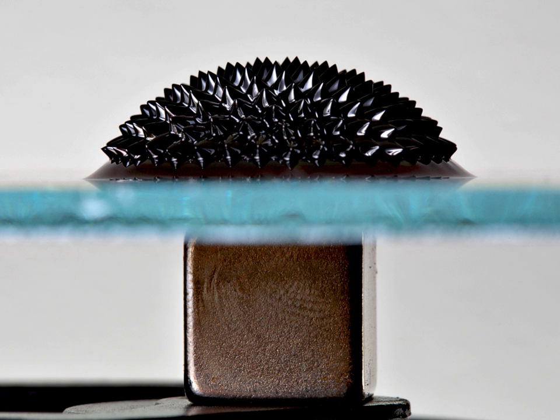They have the highest magnetic field strength and have a higher coercivity, which makes them magnetically stable, but they have a lower Curie temperature and are more vulnerable to oxidation than samarium-cobalt magnets. Corrosion can cause unprotected magnets to spall off a surface layer or to crumble into a powder. Use of protective surface treatments such as gold, nickel, zinc, and tin plating and epoxy resin coating can provide corrosion